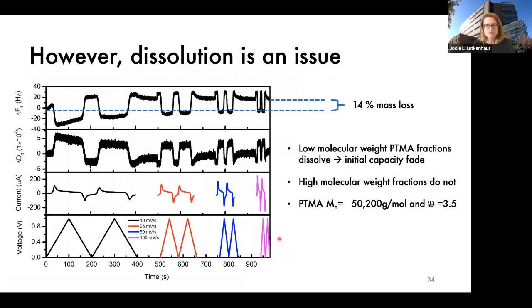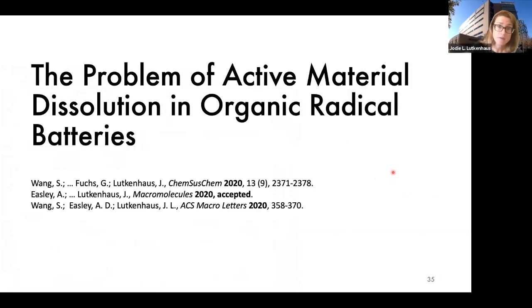I want to shift over into talking about one of the problems, which is dissolution. I think all of you are probably facing dissolution with your redox-active polymers if you're working in the solid state. If you look at our data, you see there's a drift in frequency, and the drift is too large to be assigned to an instrumental artifact. It actually has to do with dissolution of the low molecular weight fraction of the PTMA. So we have a 14% mass loss that just is not recoverable. But after that, the higher molecular weight fraction remains. So that's something we need to think about.